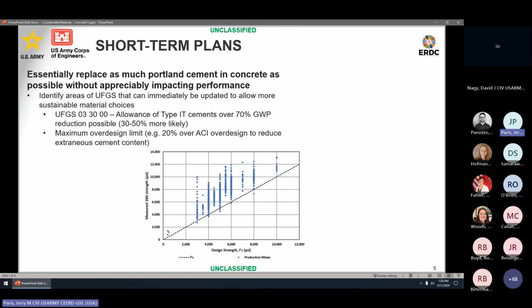In reality, concrete's a heterogeneous material, and so we have to include that over design to ensure that the vast majority of the concrete meets that minimum design strength. And so that is through ACI. So the gray line here represents the over design requirement for a given strength class of material. And so you can still see that there's a majority of mixes that are well over this line. And what that means is that it has way more cement in it than what is actually necessary.